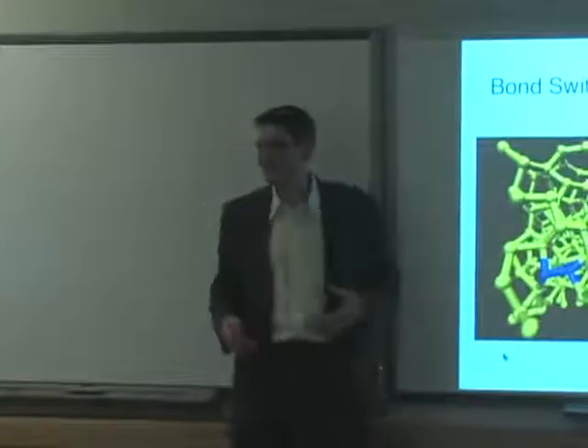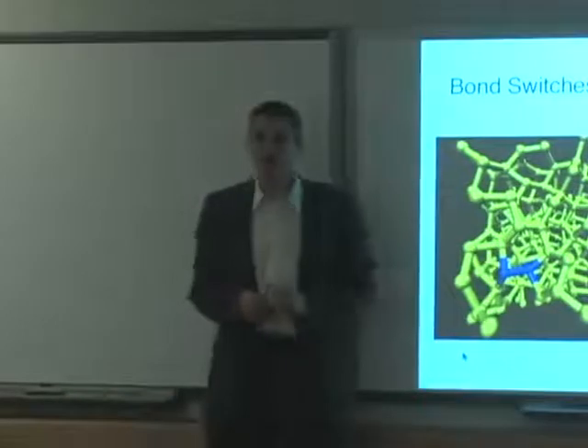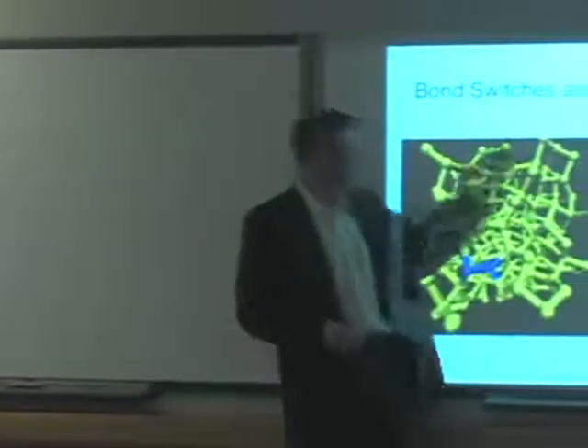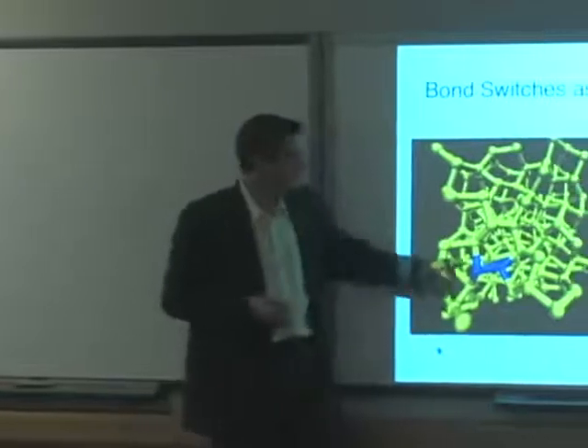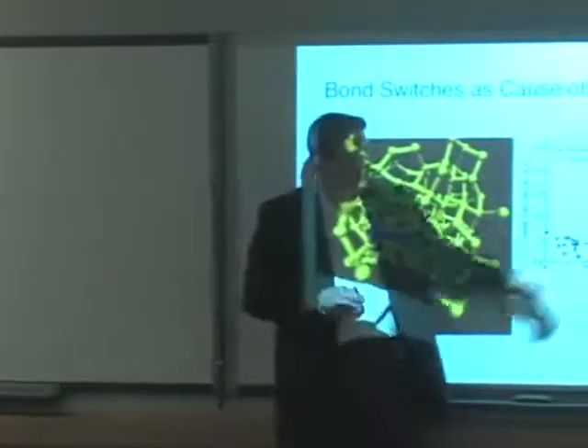See, amorphous silicon is a messy material. It's just full of defects. So making more defects sometimes doesn't cost any energy. Question is, which defects do what to those holes, right? Can we try to correlate something? And so what we did is we created lots of samples, and we rotated lots of bonds, and we plot how much energy it takes to rotate the bond. In a lot of cases, it doesn't take any energy, versus whether the new sample traps a hole or not, right? More than the previous one.